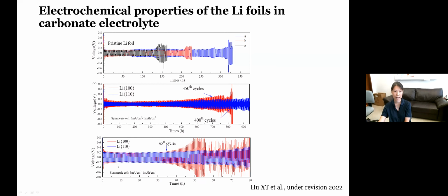We also tested the symmetrical cells at high current densities of 5 milliamp per centimeter square. And again, similar results were obtained. The blue one, which is the lithium 110, is showing much better performance than the lithium 100.